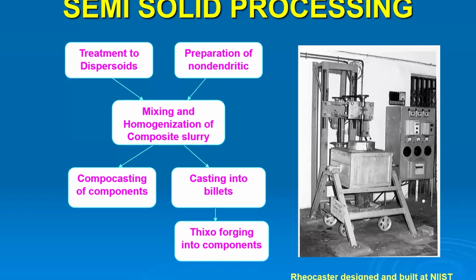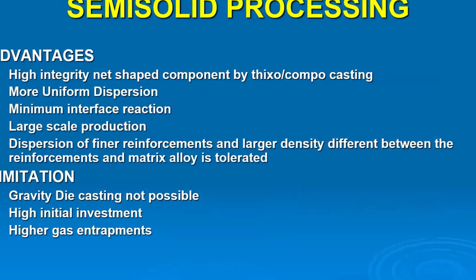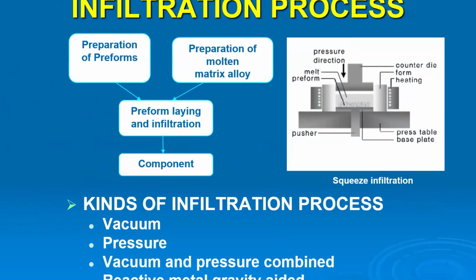You can stir it just like curd or butter. At that temperature, you can add the particles, and because of the presence of the alpha particles, the dispersion will be good. So this process can be used to make components, especially with good dispersion, even composites with very fine dispersion. Even nano-sized particles can be added, and more than that, minimum interfacial reaction and more uniform dispersion of the particles is also possible.